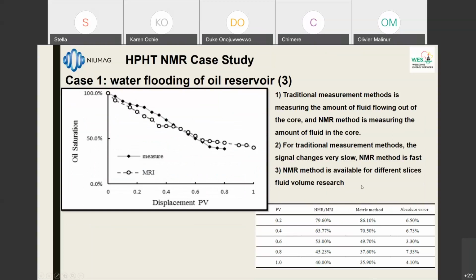So the first thing you have to remember is that NMR is measuring the amount of fluid you have inside your core, while the traditional methods measure the amount of fluid that is going out of the core. Okay, so the traditional methods are usually very slow, while the NMR is pretty fast. And you can look at the progression of your waterfront on different slices. Okay, in this case, it was a clean core, so it was a very homogeneous sandstone, so it's not very interesting.